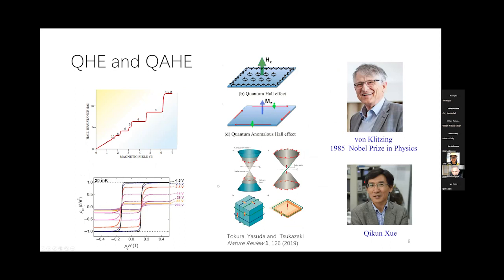At this point, Professor Xue Qikun used magnetic iron doping inside the topological insulator that will give effective mass to the massless Dirac fermion. That opened a Chern gap on the surface state and generated Chern number equals 1. And if the energy is inside the gap state, you observe a quantum anomalous Hall effect.